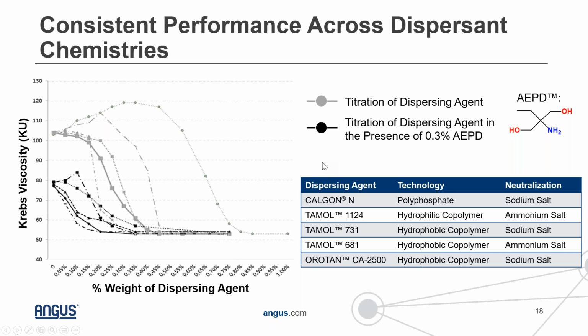And we know this is the case with many different dispersants. And it's also not just the case with AMP. Very similar experiments can be done with either AEPD or DMAMP. What I'm showing here is some dispersant demand curves using AEPD, just as an example, and also looking at it across a number of different dispersing agents. So this list of dispersing agents covers a wide range of different dispersing technologies, whether it's a polyphosphate or a hydrophilic copolymer type dispersant, and also different neutralizing agents, so whether it's a sodium salt or an ammonium salt of that dispersing agent.